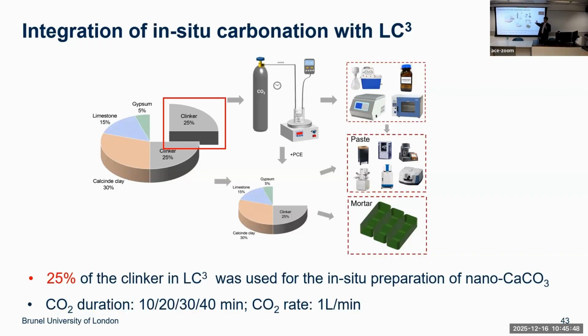We carbonate this half of the clinker in LC3, then mix it with the remaining part, making this new integrated LC3 with in-situ carbonation. We use carbon injection durations again: 10 minutes, 20, 30, 40 minutes, with an injection rate of 1 liter per minute.